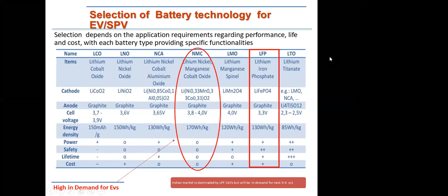Okay, then lithium iron phosphate, which is very popular in India, is giving tough competition to NMC. The disadvantage of LFP is that it has lower energy density, nearly 130 to 150 watt hour per kg in India, but safety wise it is safer than NMC, and the life cycle is more than NMC based chemistry. So you can say in the upcoming market for 3 to 4 years, these two chemistries will dominate.